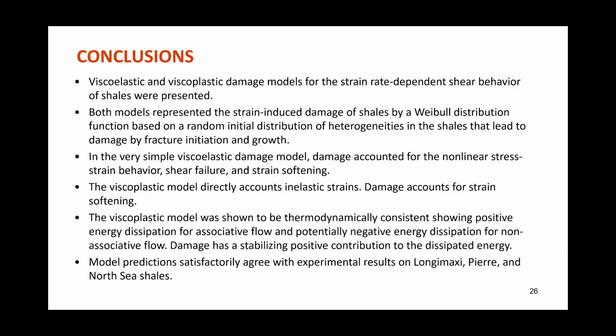Okay, all right. So let me conclude. I have presented 2 models, viscoelastic and viscoplastic damage models for strain rate dependent shear behavior of shale. Both models use damage as represented by a Weibull distribution function based on an initially random distribution of heterogeneities in the shale to model damage by fracture initiation and growth.